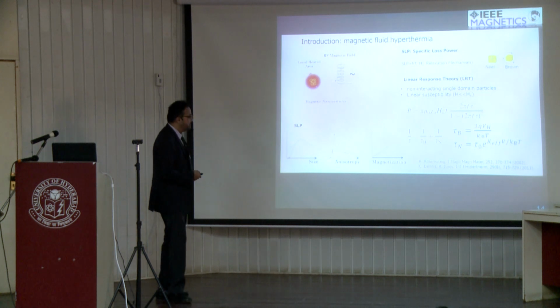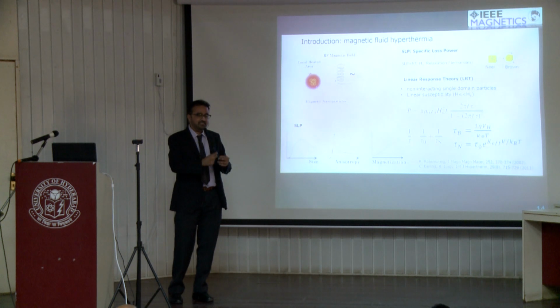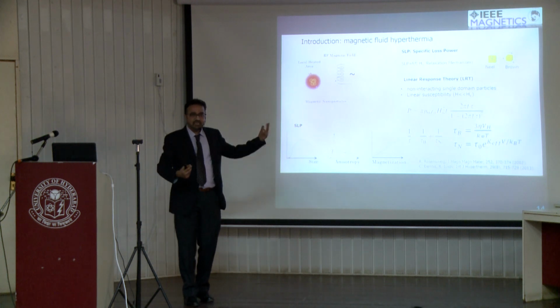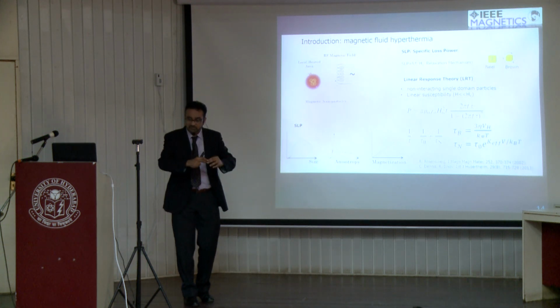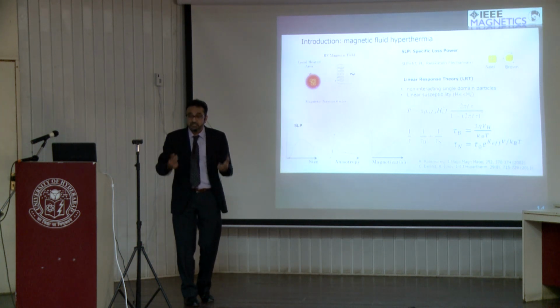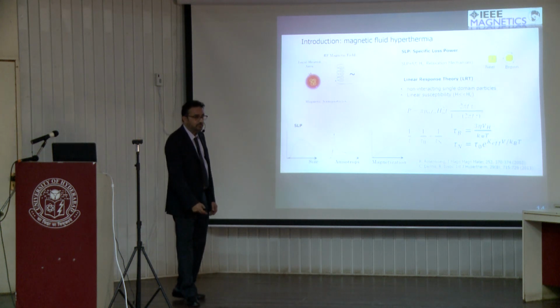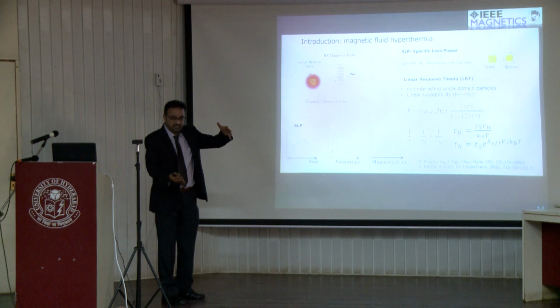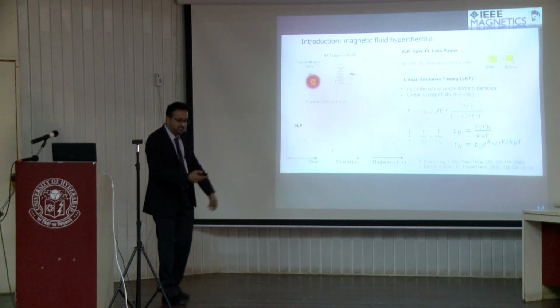And very little is known about the influence of anisotropy. What happens if you change the particle shape? And again, as I showed you earlier, when you change the particle shape, you're giving it a preferred direction, for example, and that means you're skewing the hysteresis loop, which is precisely what we want, right? We want to play with the shape of the hysteresis loops. So it turns out that anisotropy could be important, by looking at anisotropic nanoparticles to change the hysteresis loop itself and also the area, increasing the SAR.